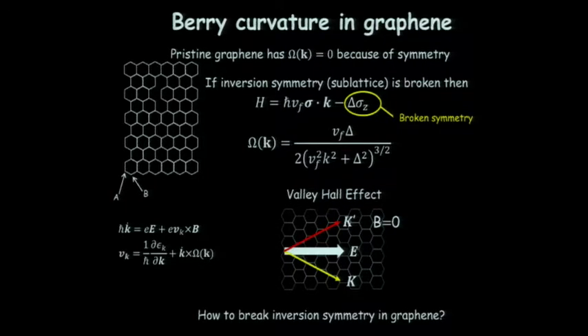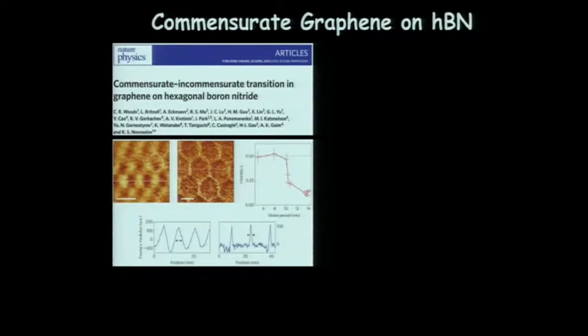So we need some way of breaking this symmetry here in the graphene. And so the way that we can do this is by matching the graphene to a lattice, a substrate, where we break the symmetry between the A and the B sites here. So these two carbon atoms right now are seeing the same environment, but if we can make them see different environments, we can break the symmetry here and open up a band gap. And so that's where the boron nitride can also come in.